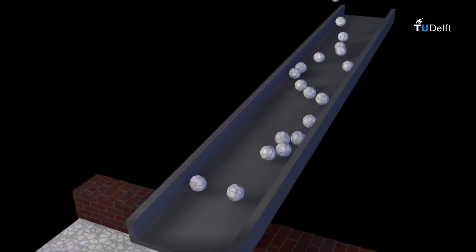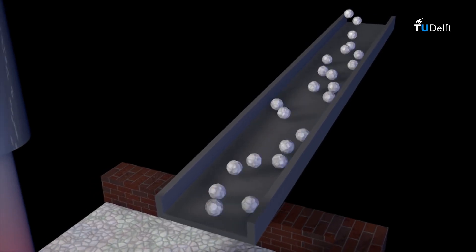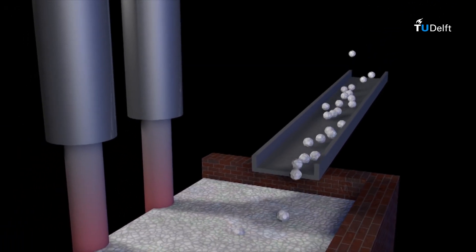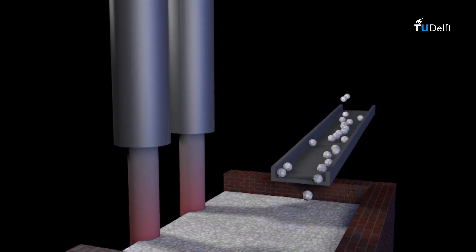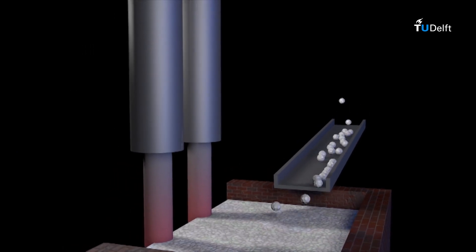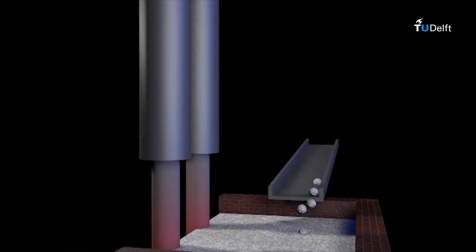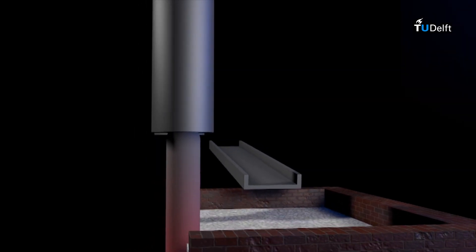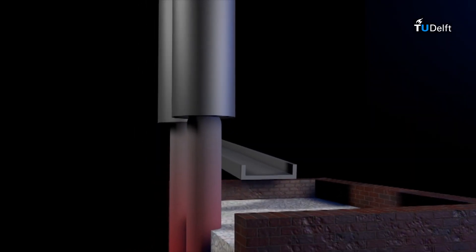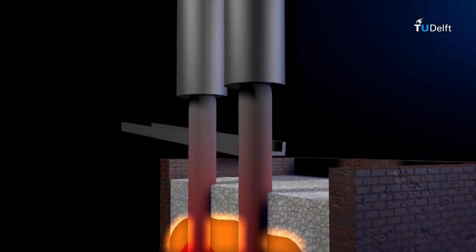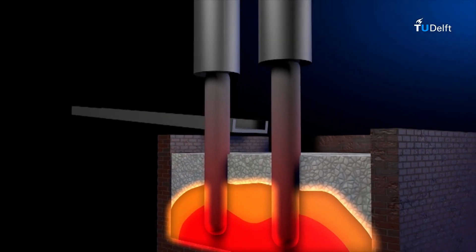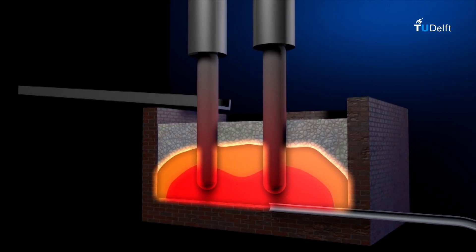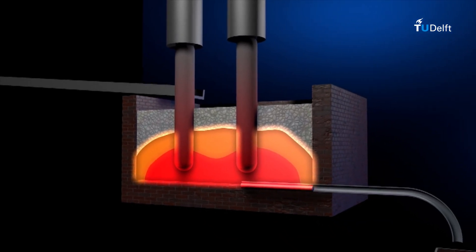In the next animation the process of making metallurgical silicon out of quartzite is shown. During production, the silicon is purified by removing oxygen. This happens in a submerged electro arc furnace where the quartzite is melted using an electrode heated up to around 1900 degrees Celsius, then mixed with carbon. The carbon source is a mixture of coal, coke and wood chips.